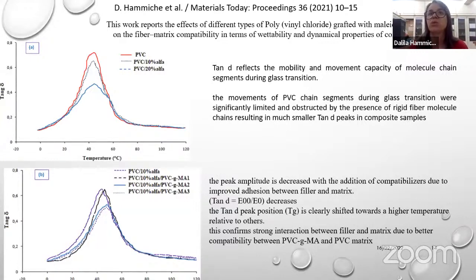This is expected because the decrease of amplitude indicates that the number of molecular segments involved has decreased, due to improved adhesion between filler and matrix. Furthermore, the tangent delta peak position, the temperature transition of the modified system, is clearly shifted toward a higher temperature relative to the others. The shift in this peak also shows that the molecular motion is restricted, and this confirms strong interaction between filler and matrix due to the better compatibility between PVC and fiber.